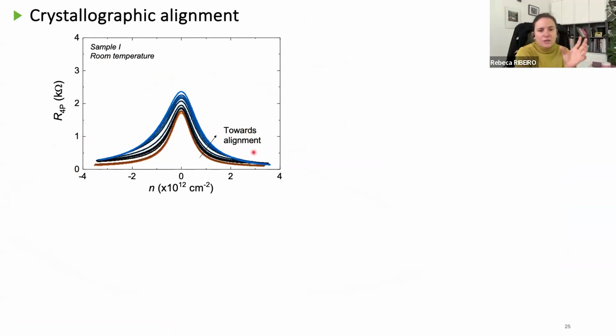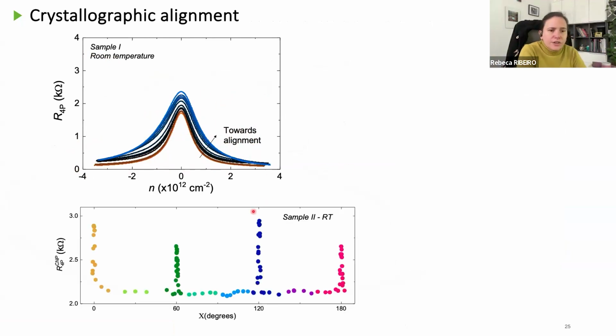It's the fact that you have a broader peak, a broader peak that will merge, in fact, with charge neutrality at room temperature. But you can still see that there is an increase in the charge neutrality point and an enlargement of this peak. In fact, if you follow this increase, you're going to see that it's periodic. Every 60 degrees, you see an increase. But if you look at this curve carefully, you already know that it doesn't seem to be the same every 60 degrees. It seems to be 120 degrees.